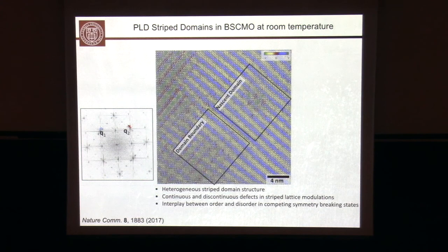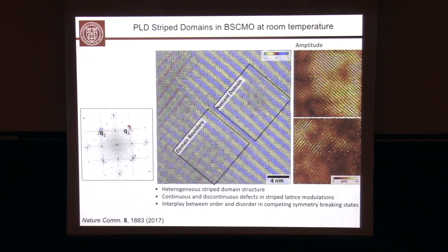And what's very interesting, it seems that there's a local competition between these two order parameters, and the way you see that is by showing the amplitude term. So this is the amplitude of the blue-yellow stripes. This is the amplitude of the red-green stripes. And so let's focus just on the center area. You see that the Q1 order is suppressed, and the Q2 order is increasing. You see that also here by green and red coming up. And so that shows you that there's some type of competition. Okay, so I want to focus for a minute on these two specific areas and want to understand what the disorder is that is involved in this.